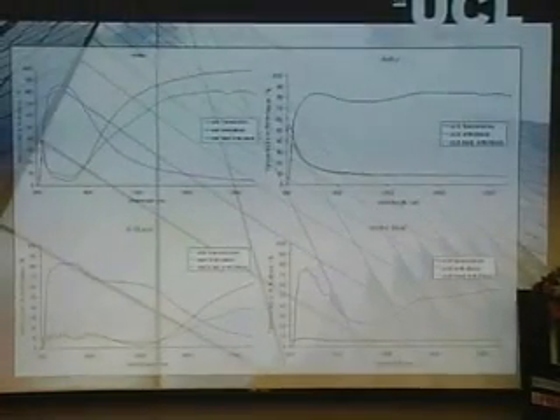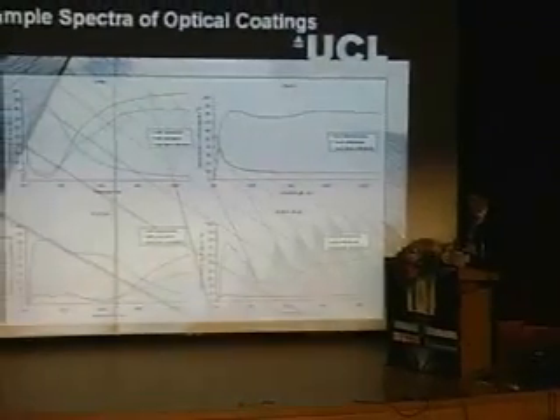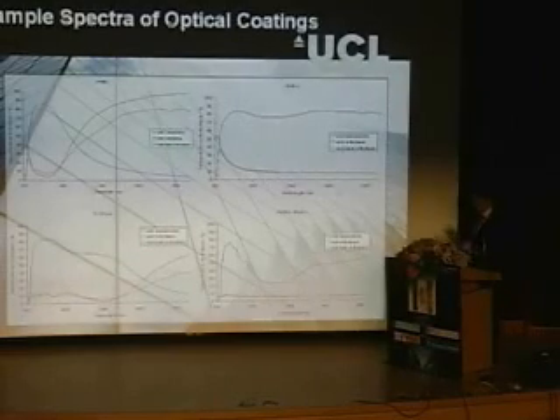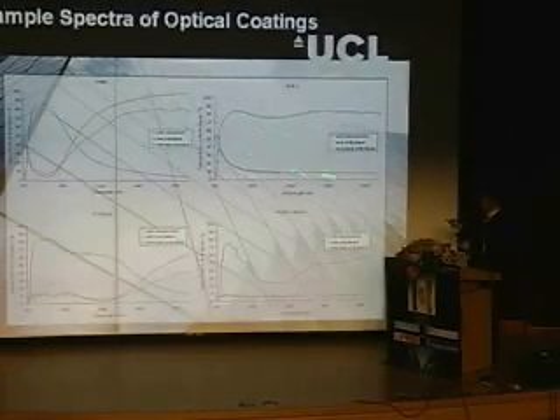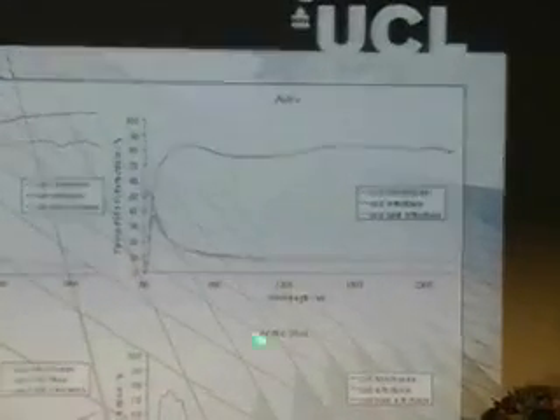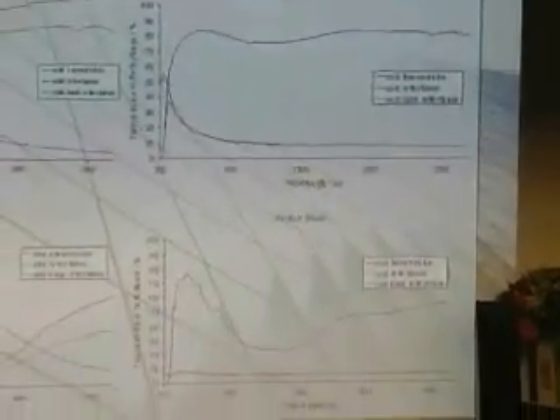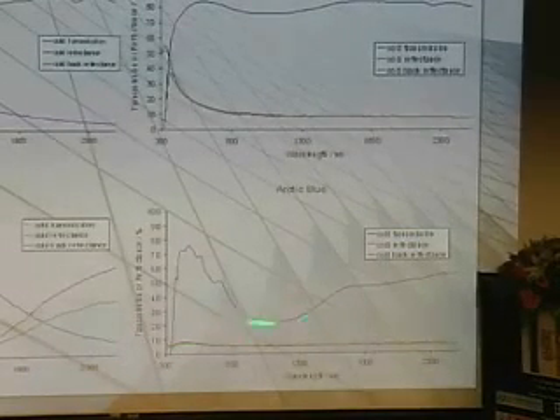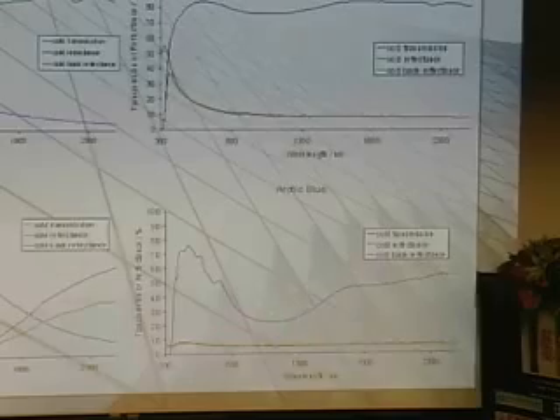This one in the top right is typical of a normal piece of glass. In this case, it's been coated with Pilkington Active, which is a self-cleaning coating. It doesn't have any energy saving properties as such, but it gives you an example of the reflection and transmission for a normal piece of glass. And bottom right is an absorbing glass. In this case it's a blue glass called Arctic Blue, which absorbs very strongly. It's not very reflective, but it's very strongly absorbing.